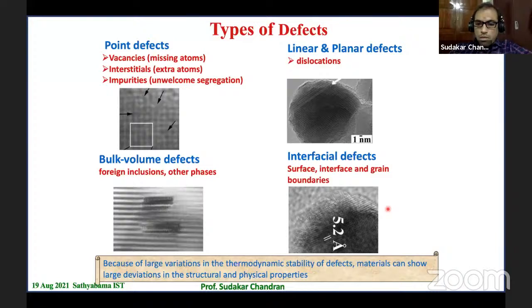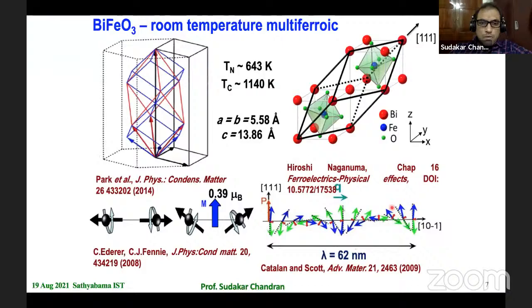You cannot ignore it. So as you see in this picture, the surface is very much disordered compared to the core. Core is very crystalline. You can see the lattice planes, well-ordered lattice planes, but the surface is pretty much disordered. Therefore, surface, interface, and grain boundaries play a very important role in controlling the properties. Okay, so with that, let me get into this first topic of bismuth iron oxide.